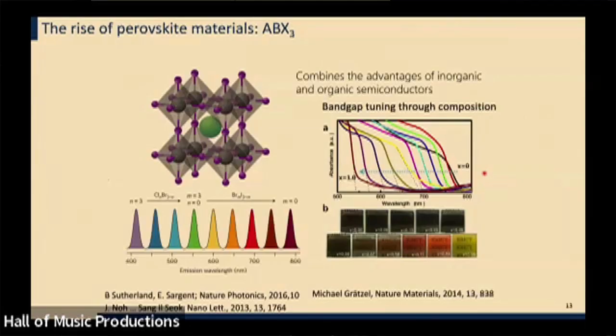So what are these perovskites up to? Well, the crystal class is ABX3, broadly speaking. And when I said organometal halide perovskites, it was that the X is a halide. Sometimes it's a mixture of iodide and bromide, or sometimes even some chloride. And these materials are very versatile. That's one striking property. So you can see here I'm showing that they can emit colors of light that span the full rainbow and that even go into the infrared. That ends up being a very powerful idea in making solar cells that can more fully harvest the full solar spectrum.